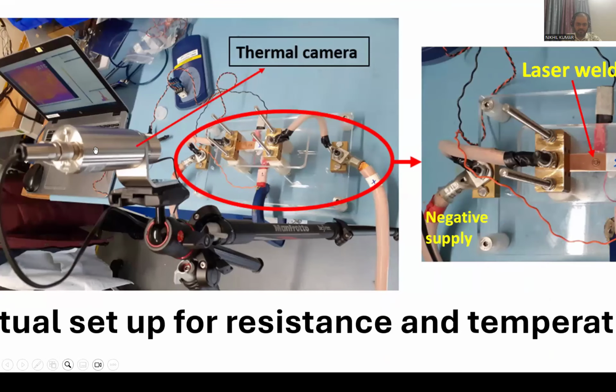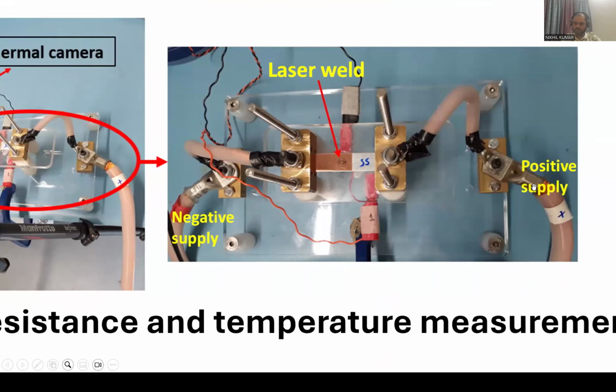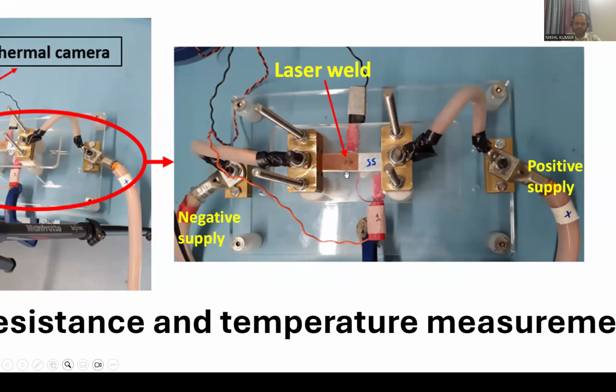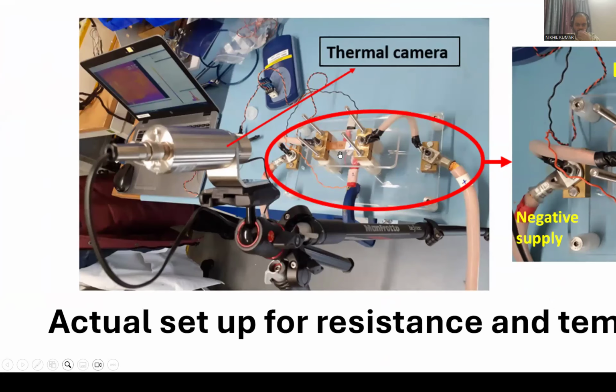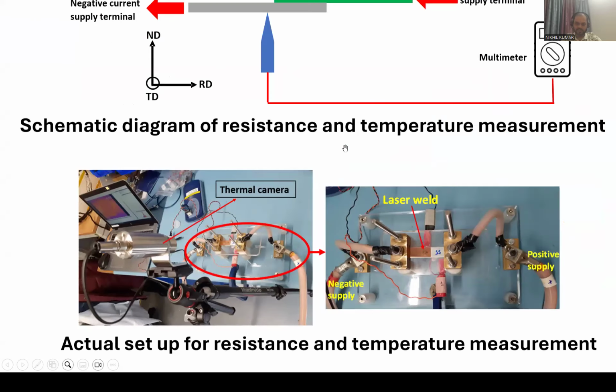This is the thermal camera. As I mentioned, I am using not a multimeter but a picologger. So with the picologger arrangement we can capture the voltage drop across the weld. There is a 2-pin probe showing underneath this sample, capturing the voltage drop across the weld, and that is recorded on this picologger. And this thermal camera is focusing on the weld area, especially to capture the temperature range, the real-time temperature.